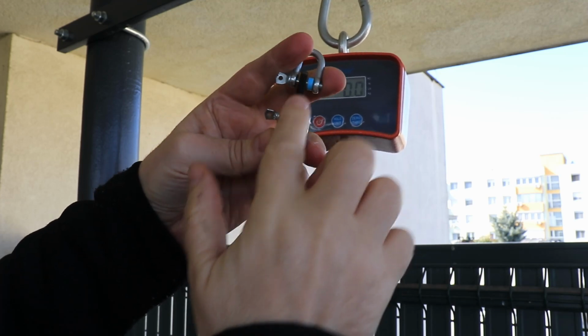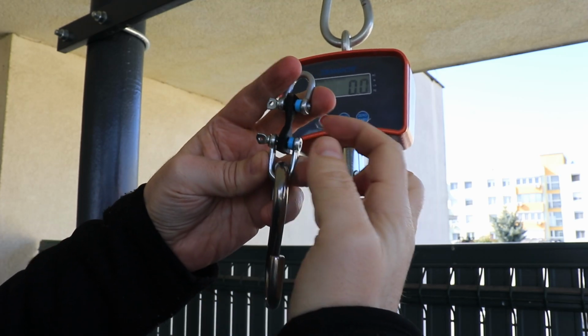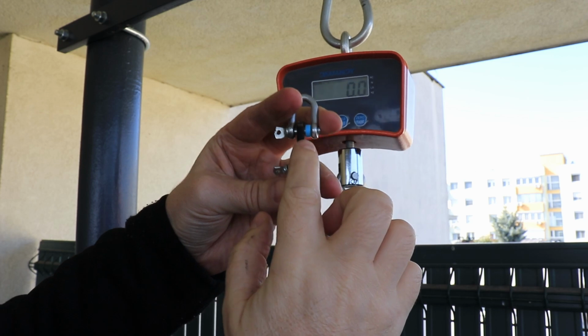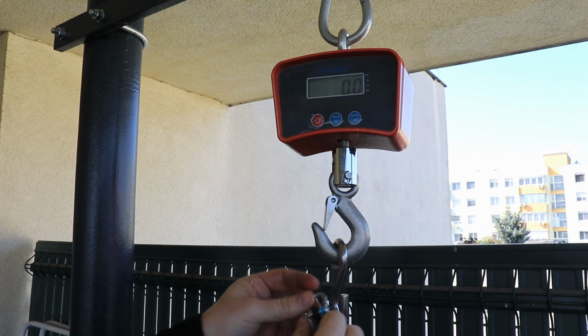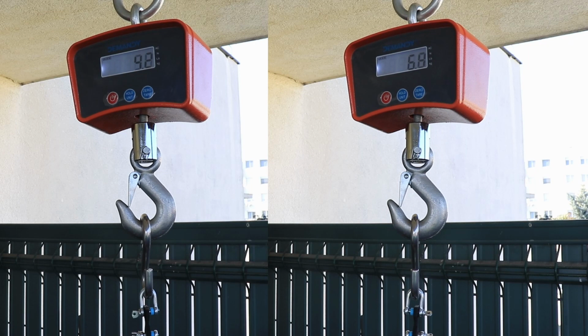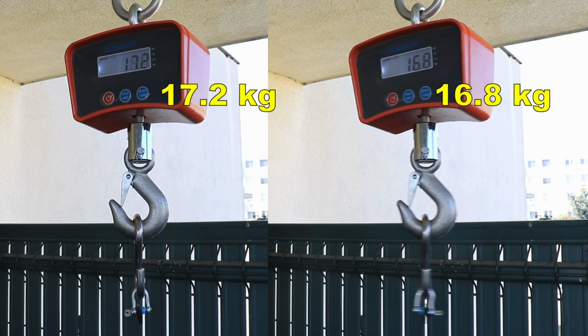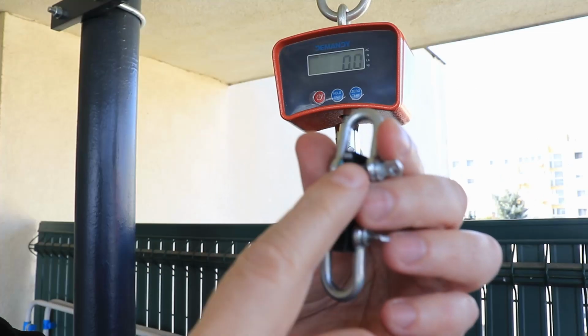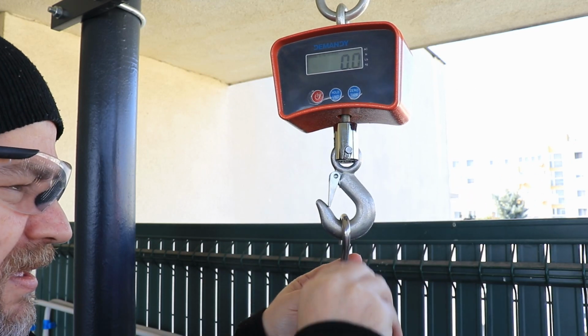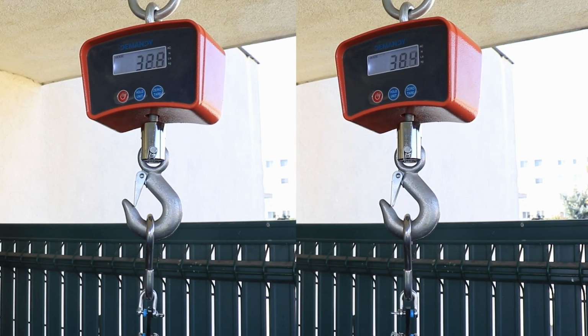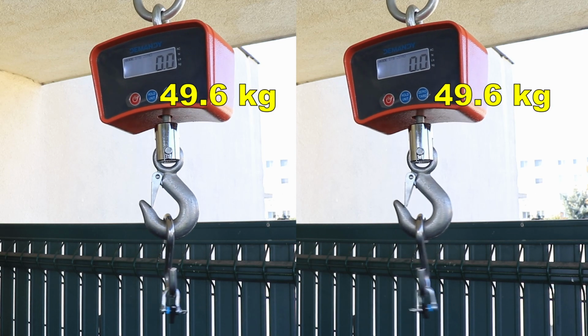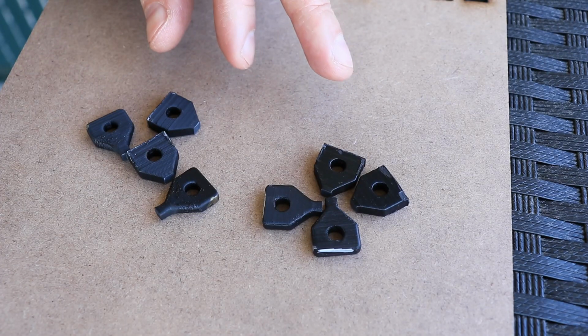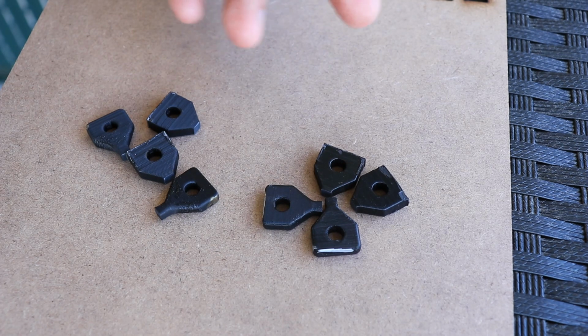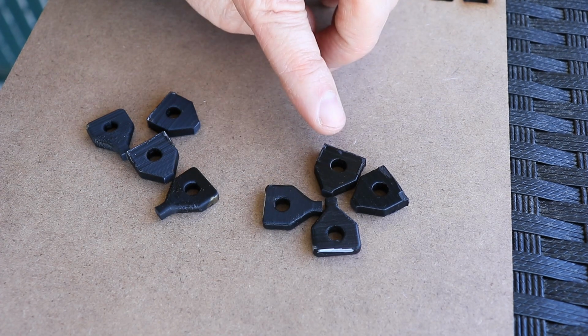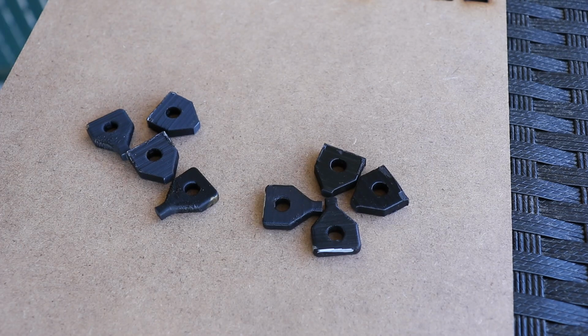Layer adhesion test. These test specimens are printed in vertical position. Smallest cross-section area is 4x4 mm. Starting with ABS Plus. And now ASA. Visually no significant difference. The numbers I can see only when I edit the footage, but for the feeling definitely the ASA was much stronger than the ABS Plus. And don't forget they were printed on the same temperatures.